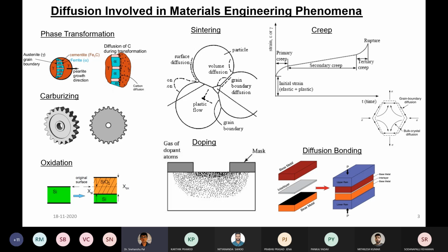One drawing is there. If you look at the bottom particle, when the particle is in contact with another particle, it looks like a grain. Through that interface, if certain diffusion is occurring, you can tell that this is grain boundary diffusion. And on the surface of the particle, there is also movement of atoms. That is surface diffusion.